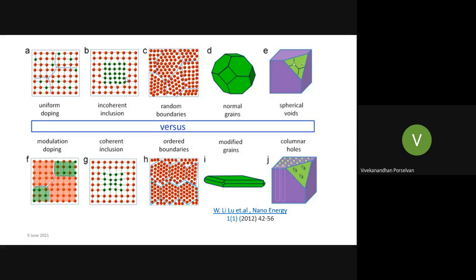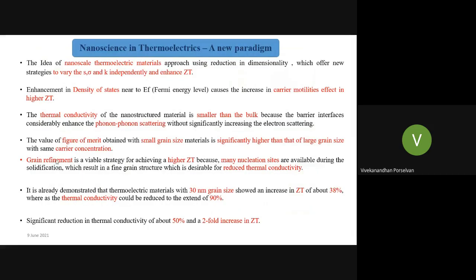Thereby, what is happening here is that it is creating a certain kind of misfit, and this misfit can lead towards scattering centers. Okay, and here we can see that we are increasing the grain boundaries, so that the grain boundaries can act as scattering centers. Similarly, a lot of approaches are being pursued to increase the electrical conductivity and to increase the Seebeck coefficient while reducing the thermal conductivity. Okay, so nanoscale in thermoelectrics.